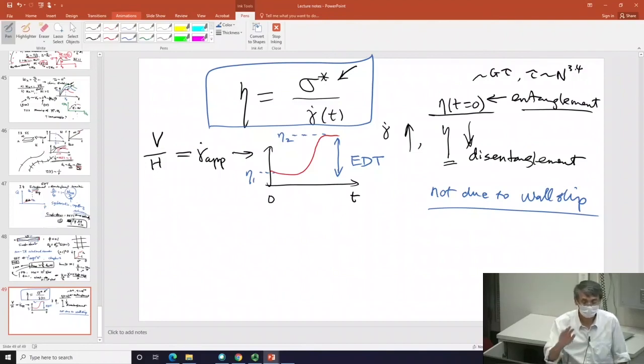I'm not going to get into the details of additional theoretical motivations for us to pay attention to any additional implications. But let me just bring you to the following point. That, of course, is something anyone who does rheology would appreciate from day one. This creep mode, as I mentioned, is a very different mode than controlled mode. It allows the upper surface to attain any velocity this material wishes to attain. You are not in control of that. You follow me, right? This is a fundamentally different way of looking at the material response compared to rate control. Because rate control, by definition, you control it.